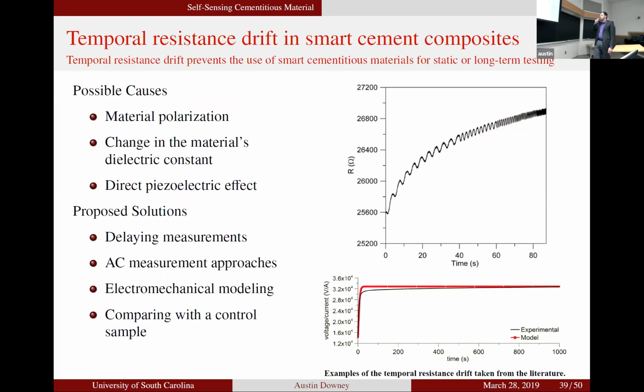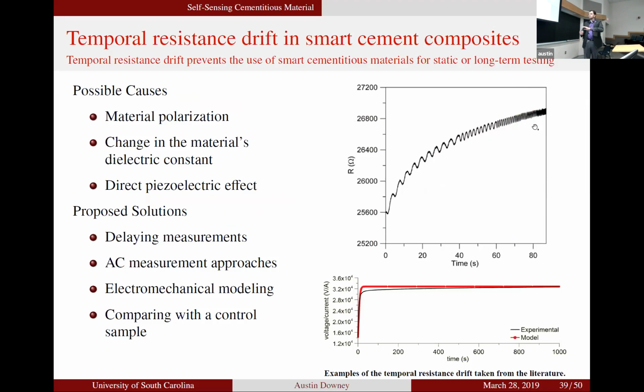While those are actually very interesting, I'm interested in long-term modeling, right? So how do we develop this for a long-term approach? And the key challenge here has actually been that this material drifts. So if you start to take a measurement of it with time, this is what you actually see, this kind of constant upward drift. And a lot of papers will just say we will leave it measuring for a couple of hours until we get to a constant place, but that's not really good enough if we want to understand this drift. So there's been some expertise with trying to model this.